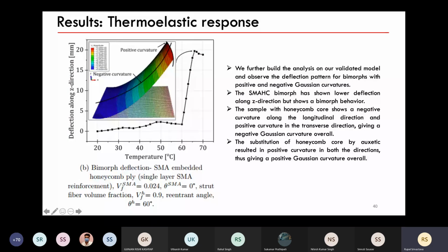Okay, so here you can see that we have 2 different curvatures. This structure is bending in 2 different directions. So this is a negative curvature, and this is a positive curvature, or vice versa. It depends upon what you are taking as positive and what you're taking as negative, as you must be studying in your mechanics of materials courses in which you have moments. So one is positive and one is negative. So it's like a saddle. A saddle is what we put on our horses to ride them. So this is a saddle shape, or we also call it something which has a negative Gaussian curvature. The curvature has a positive one and a negative one, and when we multiply these both, we get a negative one. That is why it's a negative Gaussian curvature. Gaussian curvature is nothing but the product of the two principal curvatures of a structure.